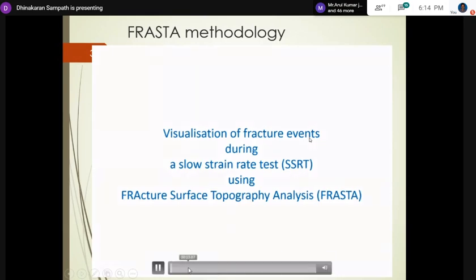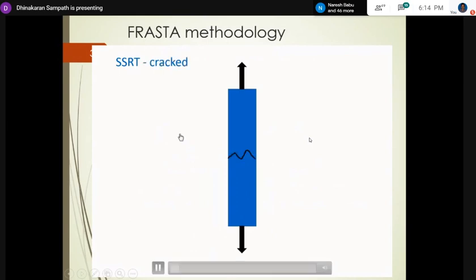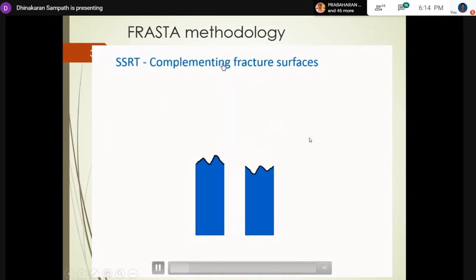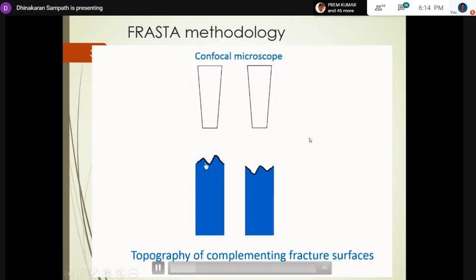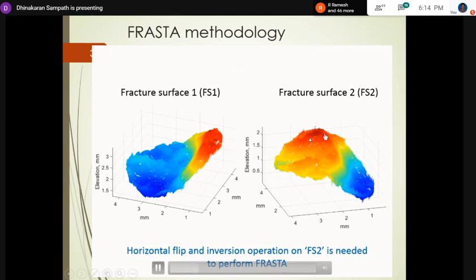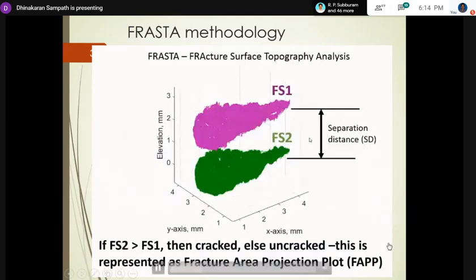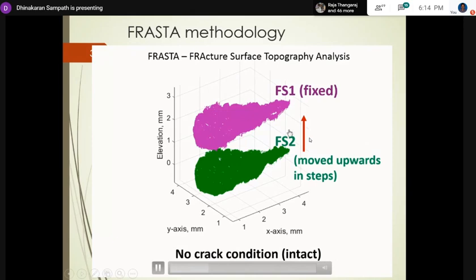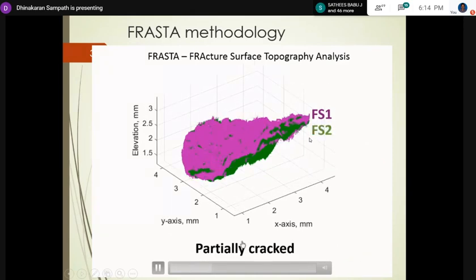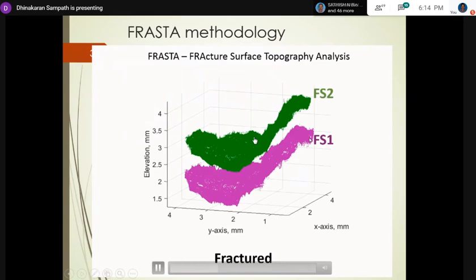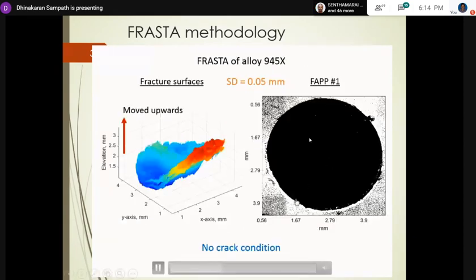So here I'm going to show the video. This is the slow strain rate test, and we have got a crack, then it fractured. These are the complementary fracture surfaces. We use a confocal microscope, which will give the depth data. That's what we call topography, and these are the topographs of the complementing surfaces. And this is the separation distance. So if FS2 is brought down and moved up slowly, at the minute it is partially cracked, it is moving up. Some places we see that it is coming out. So now it's fractured. We use this in small steps to get the